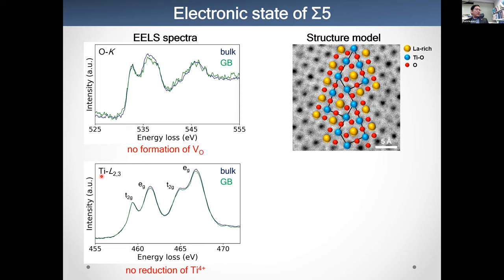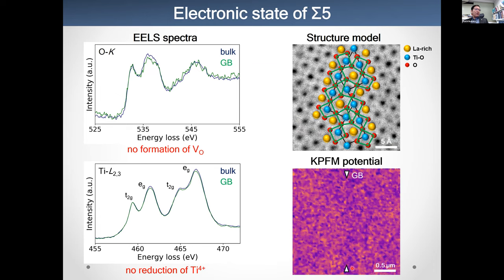We also investigate the titanium L3 edge. Green is from the grain boundary, black is from the bulk. There is no big difference. That means no reduction of titanium. If you look at the structures here again, you see the titanium. Titanium has an octahedral structure with oxygen. All of the titanium has an octahedral structure. That means six coordination numbers. So the structure is very similar to the bulk. That is consistent with no charge along the grain boundaries. This is the case of sigma 5 grain boundaries.